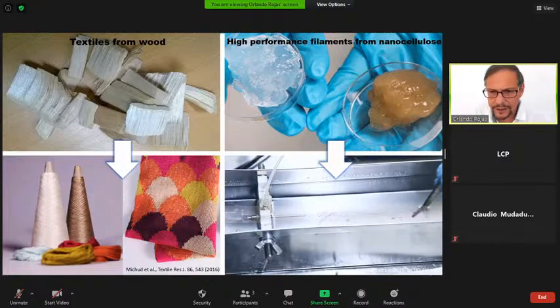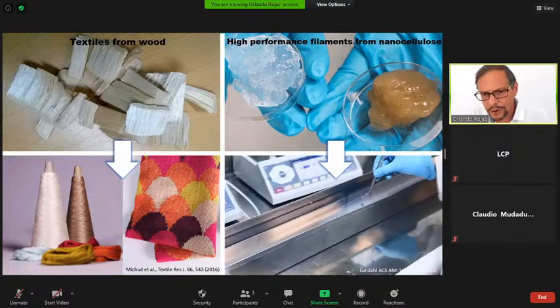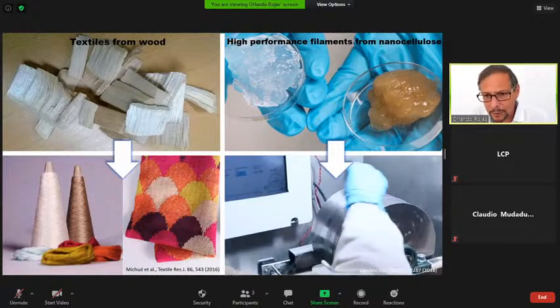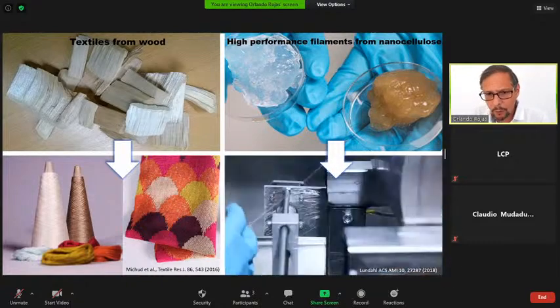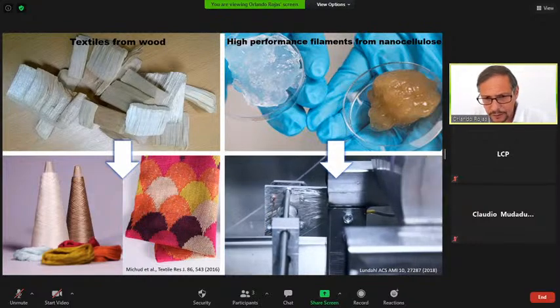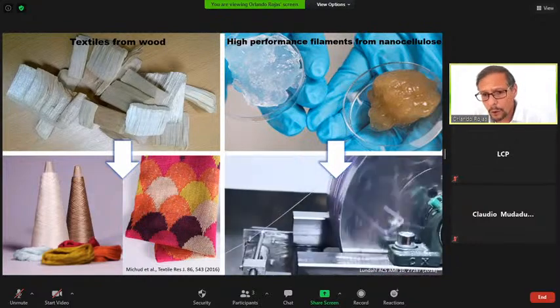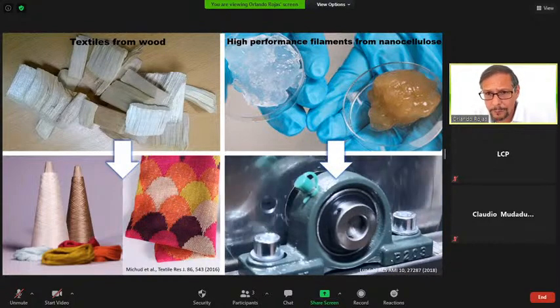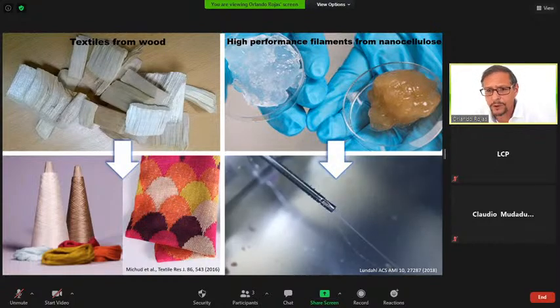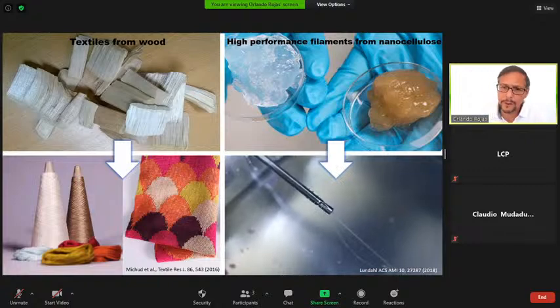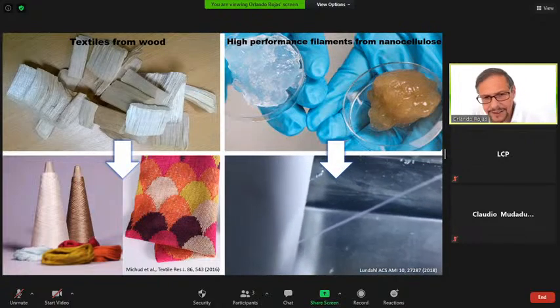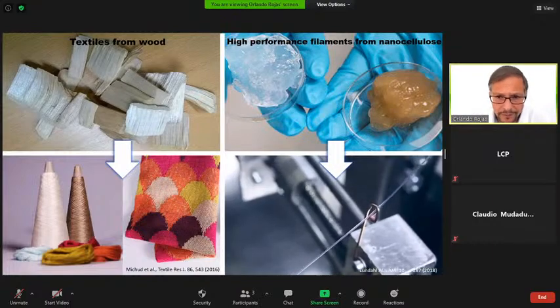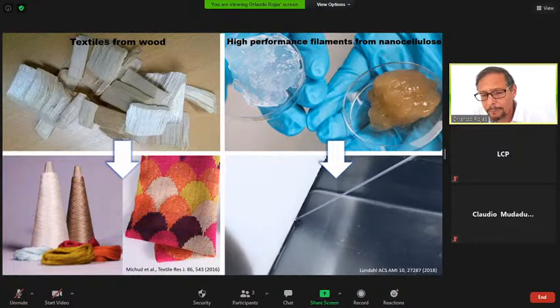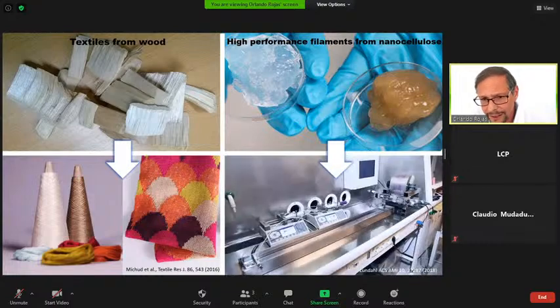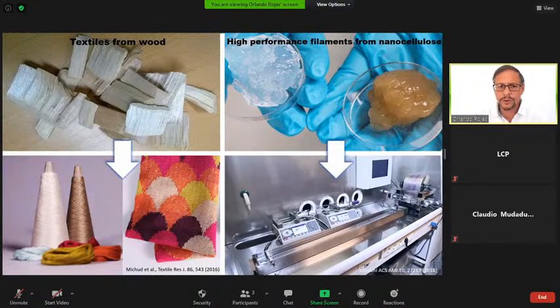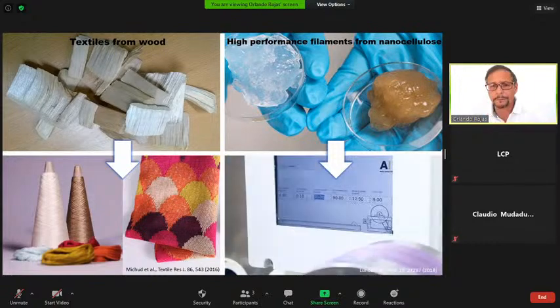Anyhow, in the video that you see in the bottom, you see how the nanocellulose can be dispersed in aqueous medium, and then using a coagulation bath that is maybe an acidic solution, also water with acid or ethanol, then you can have coagulation and produce a filament. So this is a truly green process that can be scaled up and can be used for producing a different type of filament compared to the ones on the left. Nevertheless, an important one, because it can produce properties that are quite different compared to those that are produced from cellulose dissolutions.